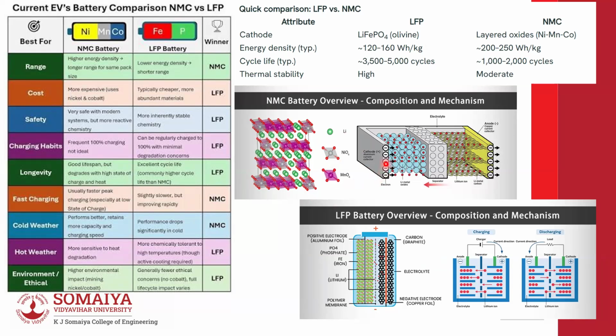So what I want you to understand is that when I say charging, the lithium will go into the anode section where you have graphite, or sometimes in NMC formats you also have graphite with silicon, carbon and silicon. Graphite being a layered structure, the lithium can easily set in inside. And when I say discharging, the lithium moves away from the anode and sits inside the cathode. So that's how charging and discharging happens in both formats.